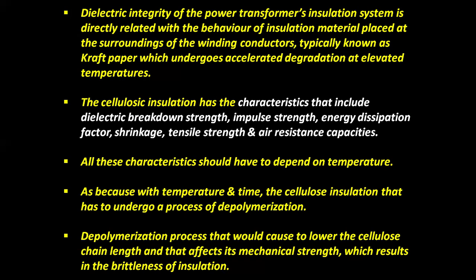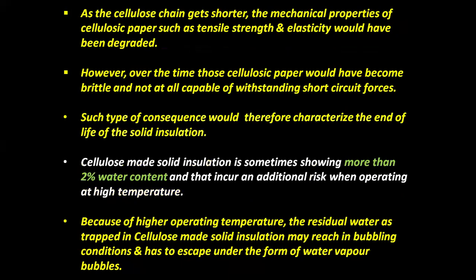temperature. Because with temperature and time, the cellulose insulation undergoes a process of depolymerization, which lowers the cellulose chain length and affects its mechanical strength, which results in the brittleness of insulation. As the cellulose chain gets shorter, the mechanical properties of cellulosic paper, such as tensile strength and elasticity, are degraded. Over time, the cellulosic paper becomes brittle and not at all capable of withstanding short circuit forces. Such a consequence would therefore characterize the end of life of the solid insulation.